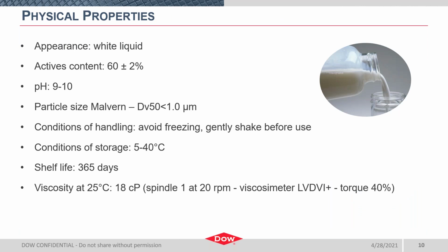The delivery of 8016 resin is consistent with your typical emulsion. It's a milky white liquid. It is pourable, low viscosity, enabling ease of incorporation, and it is stabilized at moderately high pH. The recommended storage conditions and shelf life are also very consistent with other waterborne delivered products. When considering the delivery, the differentiation is really on the solids content. 8016 resin is delivered at 60% actives, where your typical acrylic emulsions are going to range between 45 and 55% actives. By delivering this emulsion with higher actives, we're giving formulators the option for higher solids formulations, and then also we're shipping less water in every container.